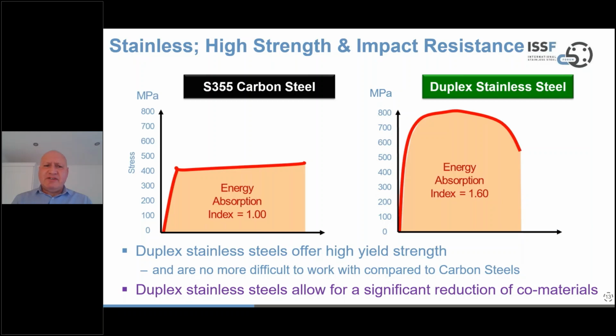Let's look at a couple of features. So here is a comparison of standard carbon steel versus duplex stainless steel in terms of strength and impact resistance. And impact resistance is effectively shown as energy absorption. So if the carbon steel is our standard and has a yield strength shown on the chart, something close to 400 megapascals or a little less, the duplex stainless steel offers a much higher yield strength. Of course, we're not quite comparing apples with apples because stainless steels yield in a different way to carbon steels. But the energy absorption characteristics of a duplex stainless steel are generally significantly higher than that of carbon steels. And these products are really no more difficult to work with compared to carbon steels. So the benefit that a duplex stainless steel brings when you're thinking about construction is not just the corrosion resistance, it allows for a significant reduction in what we would describe as co-materials.